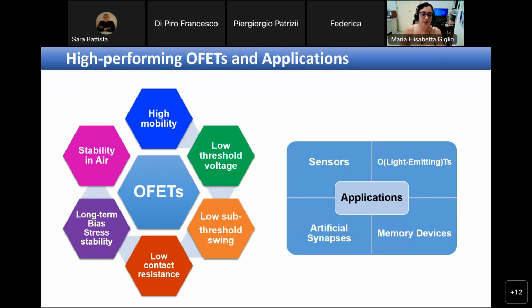So in order to obtain high-performing organic field effect transistors, we have to obtain high mobilities. The threshold voltage needs to be low, ideally close to zero. And we want a low subthreshold swing, which means that the device has to be very fast in turning on. We want a low contact resistance, between the electrodes and the active layers. They have to be stable under air atmosphere as well as under bias stress. There are a lot of applications for organic field effect transistors, from sensors to organic light emitting transistors, artificial synapses, or memory devices, but also much more.